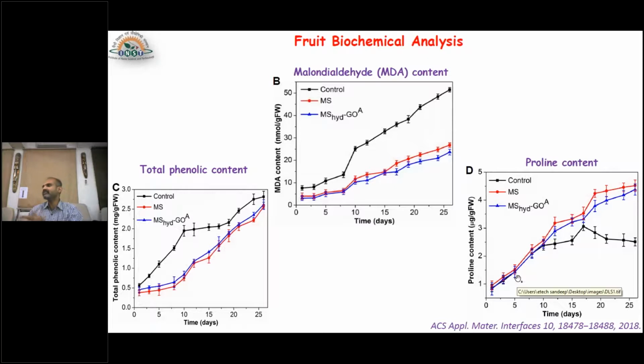And when the fruits are getting preserved, the cell membrane does not get damaged. When the cell membrane, the lipids, are not getting damaged, then the malondialdehyde production will be lesser. When it is not preserved, the membrane will be damaged, so malondialdehyde synthesis will be more. So you have to take the fruit sample and check the malondialdehyde content. As you can see in the control, there is a huge increase in the malondialdehyde content, whereas the salicylic acid and the salicylic acid composite with graphene oxide are able to preserve the fruit, so they show lesser malondialdehyde.